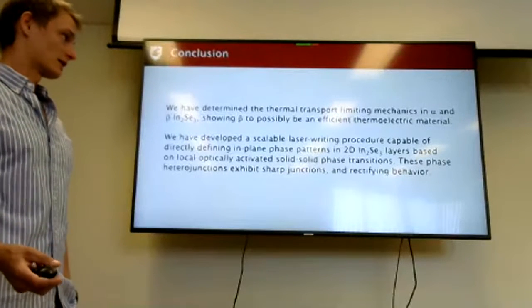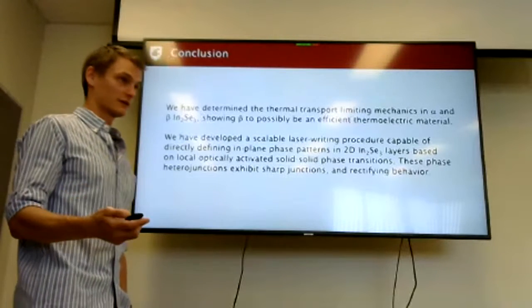In conclusion, we determined the thermal transport limiting mechanisms in alpha and beta indium selenide and showed beta to be a possibly efficient thermoelectric material. Then we developed a scalable laser writing procedure capable of directly defining in-plane phase patterns in two-dimensional indium selenide layers based on local optically activated solid-solid phase transitions. And these phase heterojunctions are sharp and rectifying.